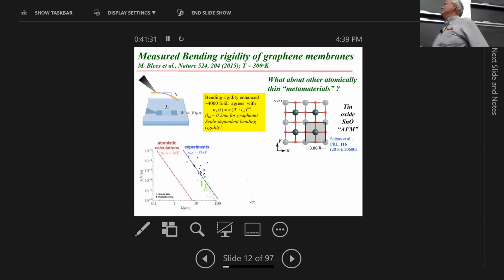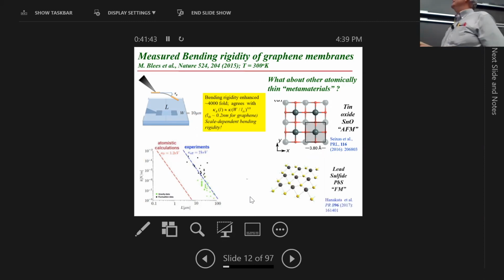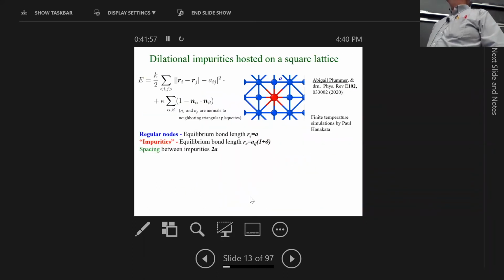And it turns out the prediction, at least at zero temperature, is that this forms a kind of antiferromagnetic state, where half of the large balls are up, half of the large balls are down. You can also have lead sulfide, and the prediction there by Paul Hanakata and collaborators is that the large balls all want to be on the same side. So that's the analog of a ferromagnet. So we thought we'd do a simulation and some theory trying to understand this a little bit better.